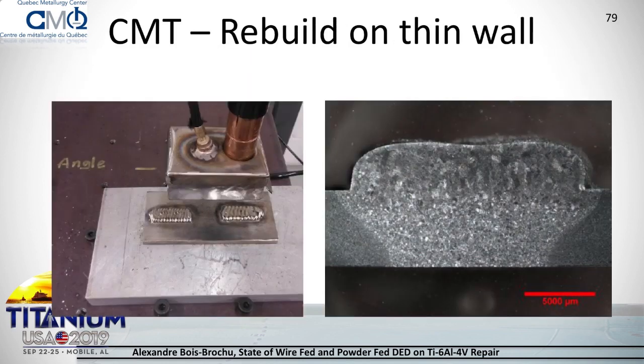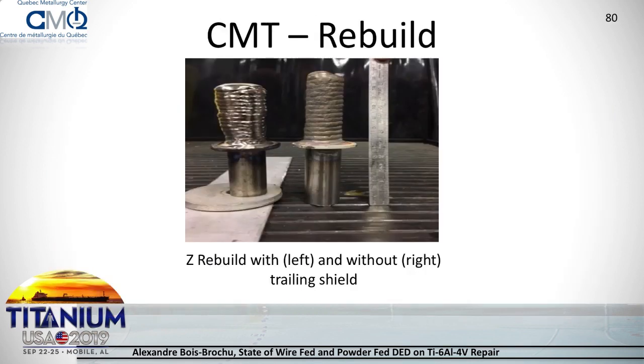And those are two examples that I'll show you of titanium. Here is a repair on a 5 millimeter thick plate with very low distortion and a 2 millimeter deposit on top of it. And the second aspect is if you need to use a trailing shield.